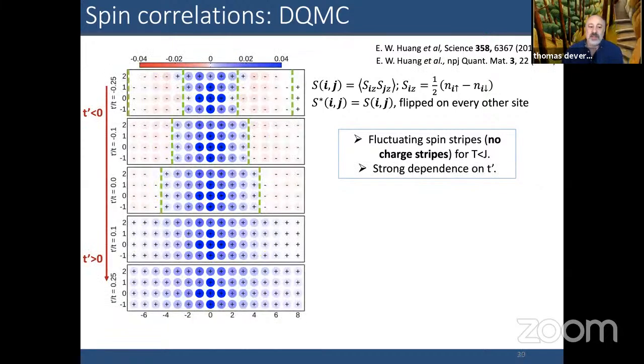But what we do see is a very strong dependence on T prime, in the sense that both the stripe period can be changed as well as the overall strength of the spin-spin correlation function. T prime being negative will have a tendency to reduce the period of the stripes, and T prime being positive will increase the period of the stripes and make it be on the order of the cluster. So this is consistent also with what comes out at zero temperature in DMRG.